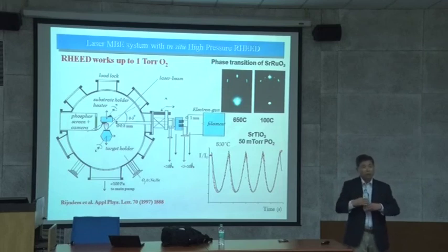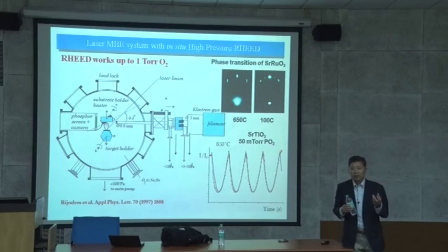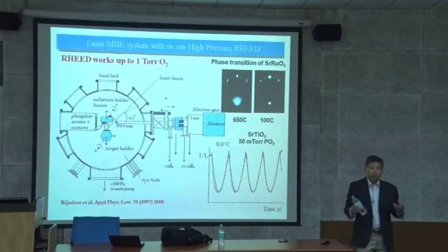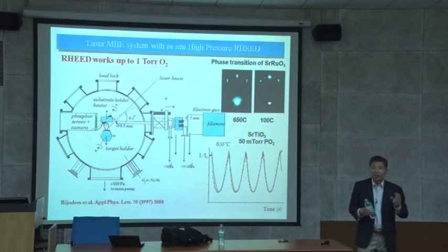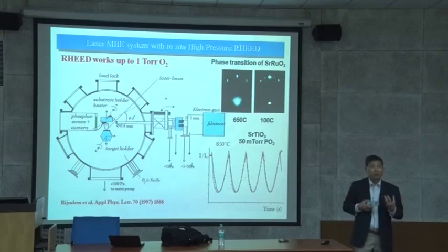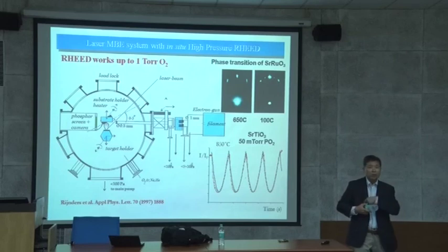You understand that? There are a lot of very trivial things in thin film growth. A lot of people just ignore small details that make a big difference to the quality of the materials you grow, no matter how hard you work. Growing here, the stoichiometry of this region is different, and coming this way you get a different composition and different material. You try to optimize hard, but you never will, because the beam profile is over focus and under focus, and this region and that region have different energy densities.